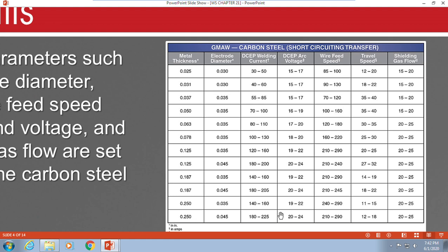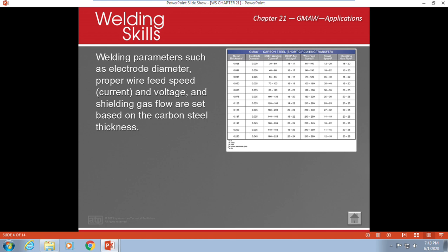So remember that short circuit, what we're doing in class, is inherently cold. So it's not going to get as hot as maybe we think it should be. But this is going to give you a good basis to what we need to be doing, okay? So it's telling us current, 140 to 160 amps, 19 to 22 voltage, 240 to 290 on our wire feed speed. Okay, travel speed, this is kind of negotiable because the average person welds between 6 and 8 inches per minute. So sometimes when we see a very quick travel speed, it means we need to be moving, otherwise we're going to burn through this stuff. And remember, this isn't all set in stone. This gives you a good jumping off point if I'm not certain.